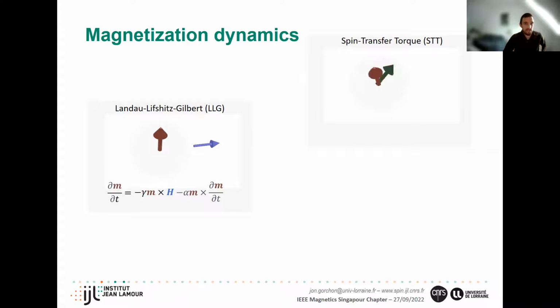Here the idea is that you just send conduction spins, and through the exchange interaction with the local magnetization, you can torque the magnetization. And you can get two different torques. One is what we call the damping-like torque, that has this geometry. And then you have the field-like torque, which is closer to what you get with the field. So M precesses around the injected spin density. And the ratio between these two torques depends a lot on the materials and the interfaces.